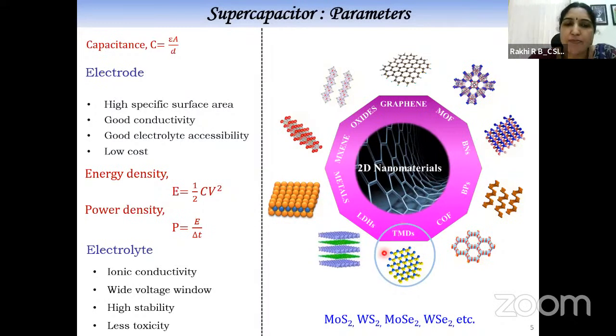Actually, transition metal chalcogenides, maybe most of you know, are 2D materials with similarities to graphene in their structure as well as electronic properties. These materials have MX2 stoichiometry, where M represents a transition metal from group 4 to group 7 in the periodic table. That is, M can be molybdenum, tungsten, or titanium. All these can be M. And X refers to a chalcogen, such as sulfur, selenium, tellurium, all those.